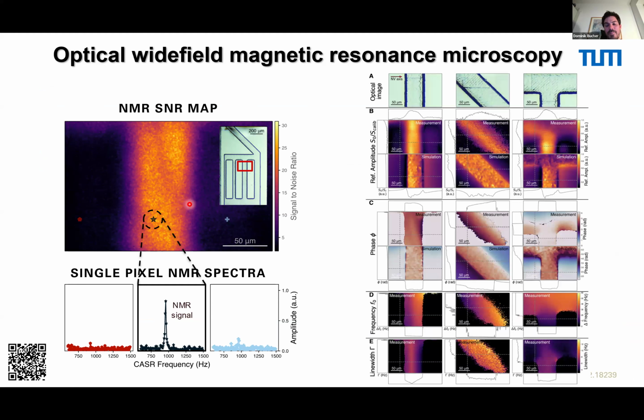As we told you before, the distance from the surface of your NV center determines the detection volume. If you have this 10 micrometer thick layer, you roughly detect 10 micrometers in the Z direction. This sets your spatial limit. So this is a 10 micrometer layer. I think it's around 10 to 15 parts per million doped. So this used radiation, I guess electron radiation. Radiation, exactly, the standard thing. Exactly. Okay, I see.